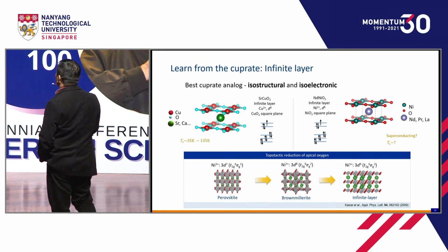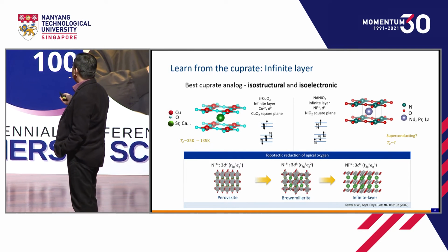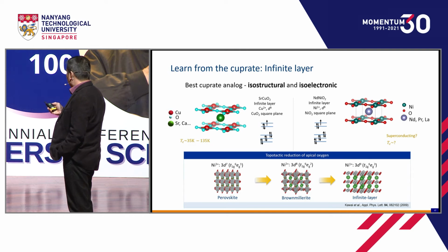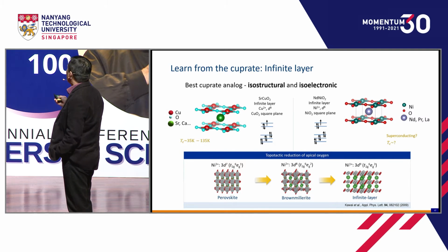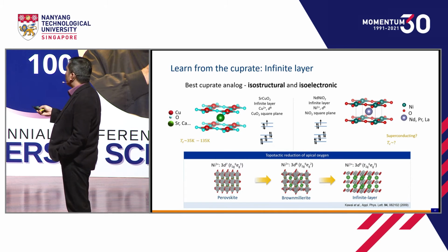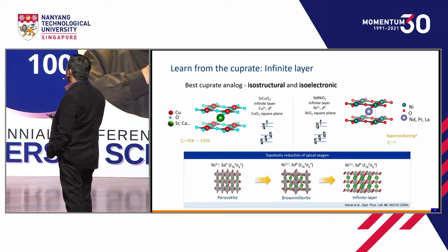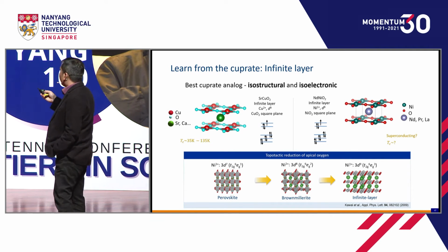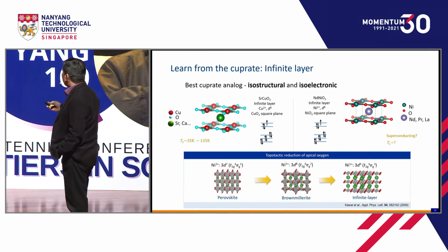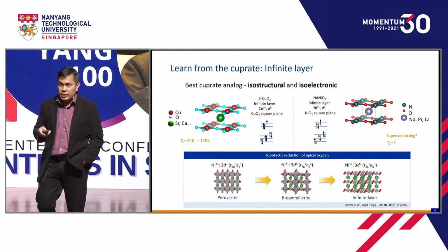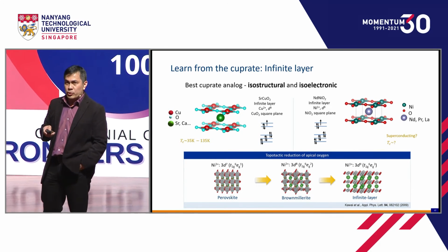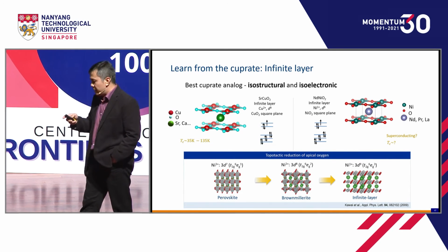So if you can produce this infinite layer in the case of the nickelate, you can basically have nickel 1+ at the end. The structure will be exactly the same as this infinite layer of the cuprate, and the electronic count of the 3d orbital will also have 9 electrons, okay? But to be able to achieve this infinite layer of the nickelate, you have to change the structures, you have to remove the atoms in a controlled way, and this is the most difficult aspect of producing this infinite layer structure in the nickelate.